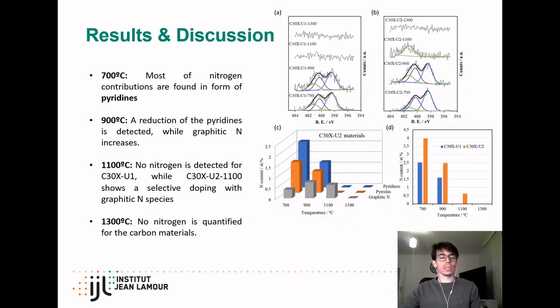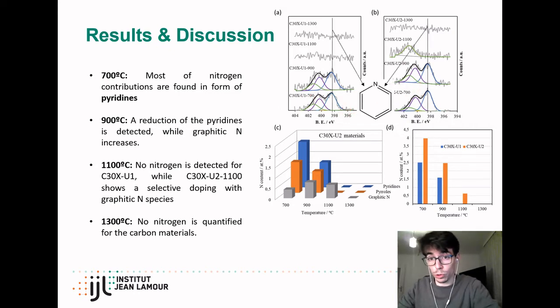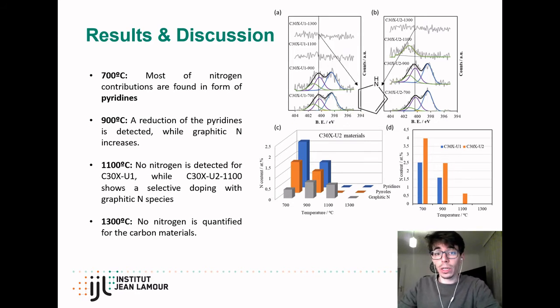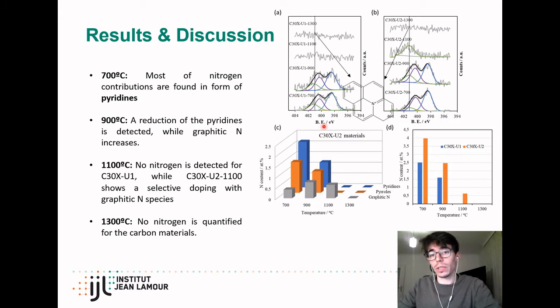But since the most important aspect of this work consists of the selective enrichment of this material, we have followed the nitrogen oxidation state through XPS. As we can see in this slide, in figures A and B, the bottom part, the samples obtained at 700 degrees show three contributions: pyridine species in blue, pyrrole species in purple, and graphitic, also called quaternary, nitrogen functional groups in green. But when we increase the temperature of the heat treatment up to 900 degrees, we can observe a decrease of the pyridine content while an increase of the graphitic nitrogen functional groups.